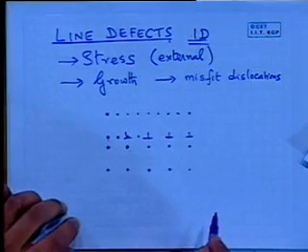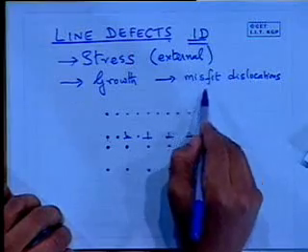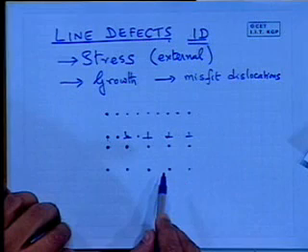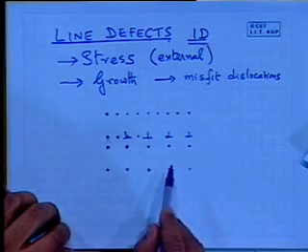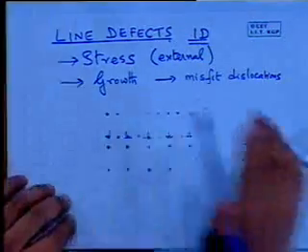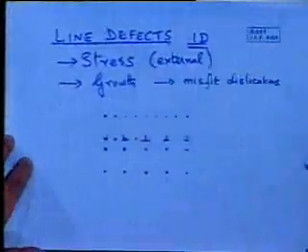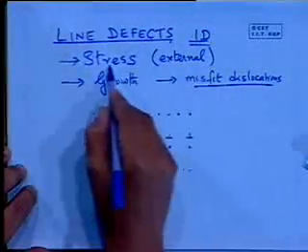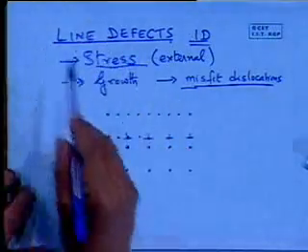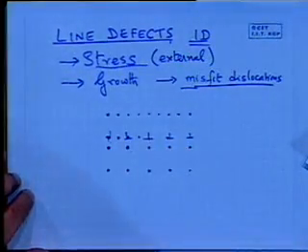These are called misfit dislocations because they accommodate the misfit in the lattice between the film that is being grown and the substrate that is at the bottom. And all these dislocations, a periodic array, will lie in this plane. So I've got this growing on top of this, and the dislocations all lie at the interface. So the misfit dislocations lie just at the interface. These are produced during growth, and then there are other dislocations that are produced by stresses in the crystal.